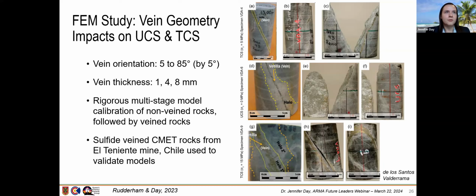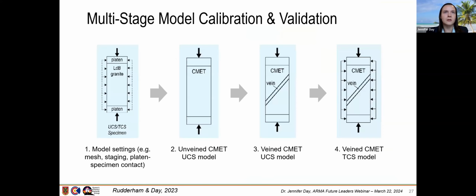In this study, Giselle looked at modeling vein orientations of 5 to 85 degrees in 5-degree increments with respect to the core axis, and looked at vein thicknesses of 1, 4, and 8 millimeters. It involved rigorous multi-stage model calibration of non-veined rocks and then veined rocks. And we used lab test data available in the literature on the sulfide veined CMET rocks from El Teniente to validate these models and carry out our analysis.